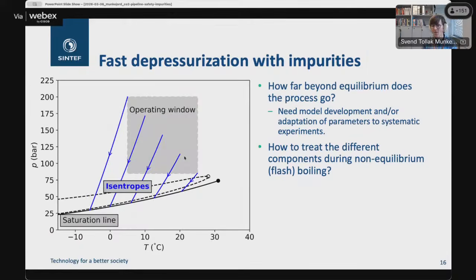Okay, now if you have a pipeline and you want to consider different operating windows and how this will influence running fracture, it's useful to make a plot like this. So fast decompression will be isentropic, so that's why we illustrate various isentropes here. And you can see on a summer day, for instance, with more than 20 degrees and a pipeline with a low pressure, you can hit the 2-phase region at a higher pressure than for a cooler day and a higher pressure. So in effect, for running fracture, a lower pressure in the pipe can be more severe than a high one, which is counterintuitive until you've seen this plot.